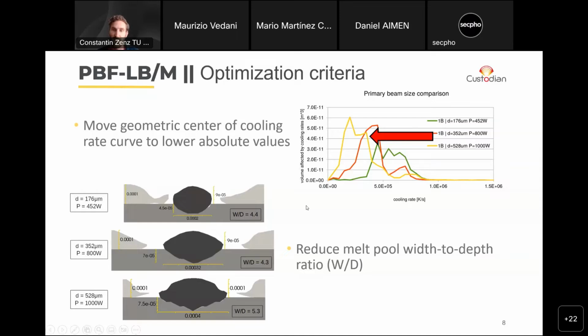So this is just how fast does it cool, Kelvin per second, the volume of material. We have three plots here, and this is just how much volume is affected by what cooling rate. You can see this is, for example, 1 million Kelvin per second. And we have here, for comparison, 3 different sizes of a beam. This is just one Gaussian beam. The green line is a very small beam diameter, and we just increased the beam diameter to some medium and some large size beam diameter.